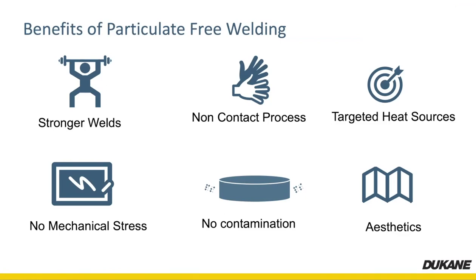No, it is, but I can touch on that briefly. There's a couple different reasons. One with hot gas welding, that's basically a form of thermal welding. With basic hot plate and IR welding, we run the risk of either reducing material that's coming together in the joining phase or oxidizing or degrading the material because of the high heats used in infrared welding. With hot gas welding and with laser welding, we kind of isolate oxygen from the weld joint, thereby giving you stronger material or reducing the risk of reducing the strength of the material when we put it together.